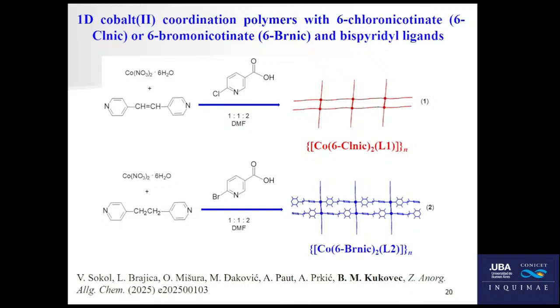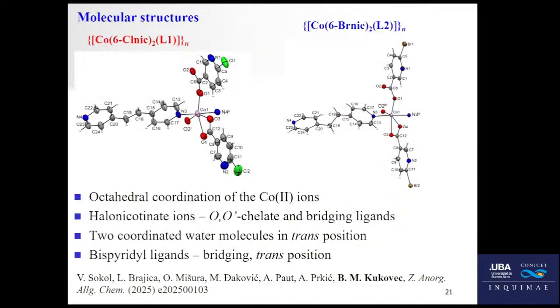Yeah, and in this case we had 6-chloronicotinic acid and 6-bromonicotinic acid. We also got two different coordination polymers. If you look at them, these are the asymmetric units. In both cases, the cobalt is octahedrally coordinated.